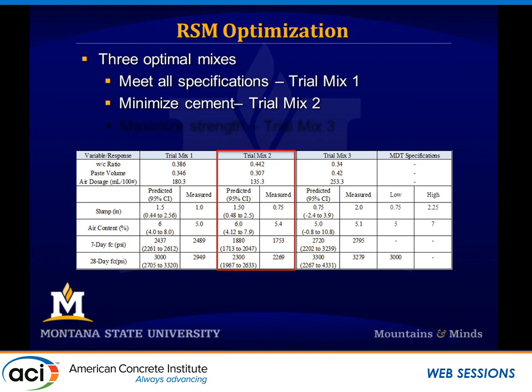And so this one, we predicted a 1.5-inch slump. We got 0.75. So again, within the confidence interval and within MDT specifications, we got a 5.4% air, and 6% was what our target was. And instead of 2,300, we got 2,269 at our 28-day strength. Again, it was right on, right? We were pretty excited about that. We said, one more. Let's do another one. Let's just maximize the strength that we can get out of this thing.